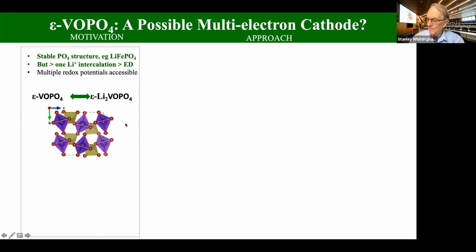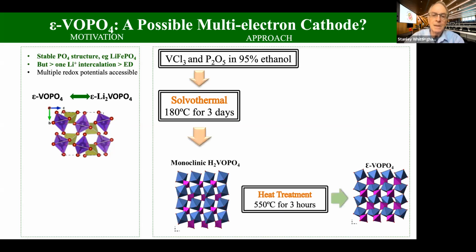And we spent a long time trying to make this material. In the end, the student found a good way to make it electrically active. She made this by a route that we've been pursuing for the last 25, 30 years. This is what we call a soft chemistry synthesis. It's about 200 degrees centigrade. We can use water, or in this case, we used 95% ethanol with vanadium trichloride and phosphorus pentoxide. You cannot use pure ethanol because it will reduce the vanadium too far. But this reaction is easy to carry out. The pressure in this reactor just comes from the solvents, so we don't put any external pressure. And this temperature is a typical waste heat temperature in a chemical plant or refinery, so it's essentially free.